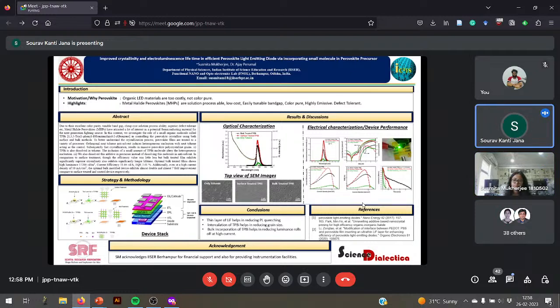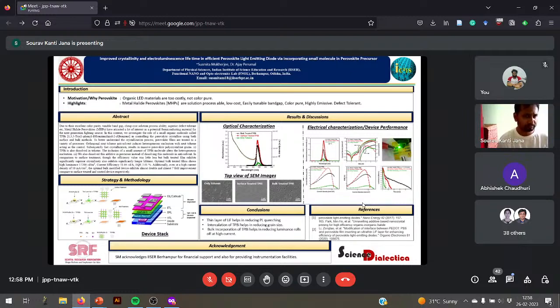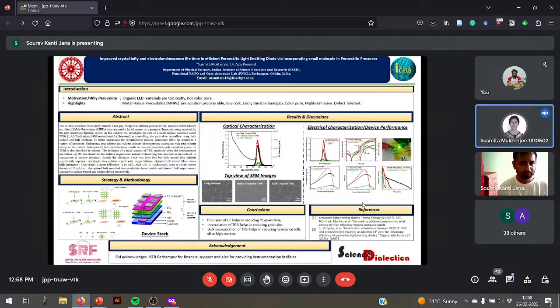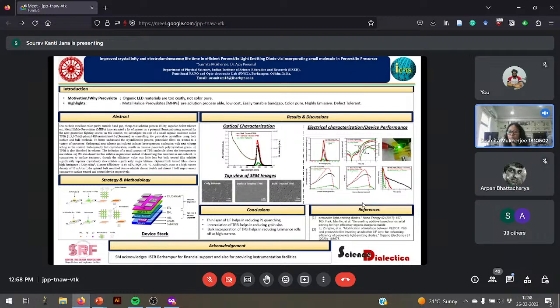Sushmita, can you explain how the degradation process happens when current is passed in a perovskite device? Sir, if I give a high bias, it leads to high current density, so there will be Joule heating. The device will heat up. After that heating, my exciton, the electron and hole pair, will not stay a pair at the end. It will dissociate, or only one charge will be left. So it will not be radiative recombination; it will be non-radiative recombination. Heat will be produced. That's why it will degrade.